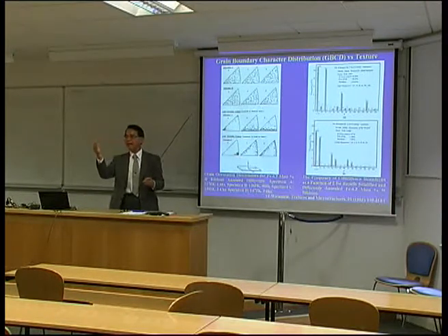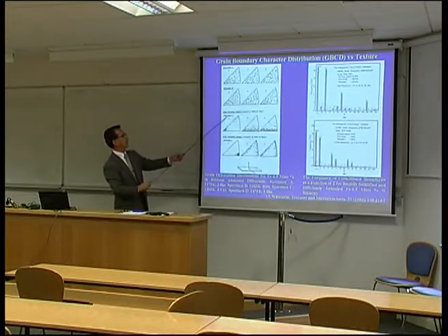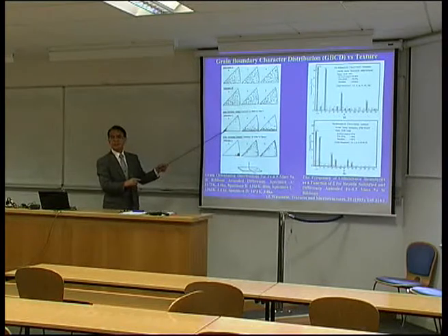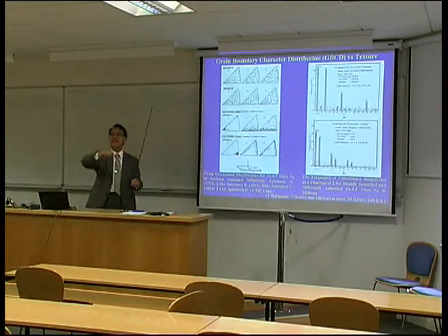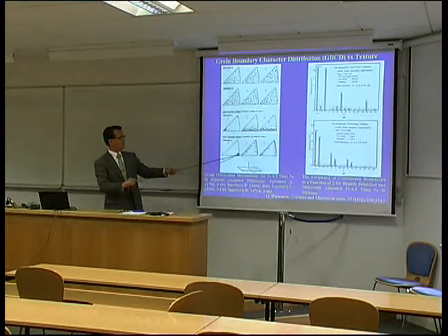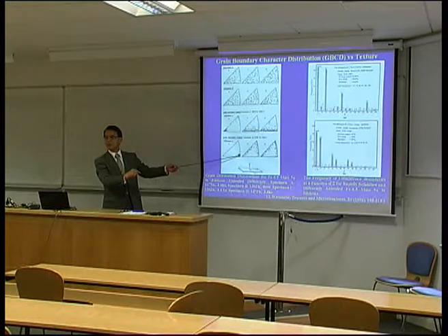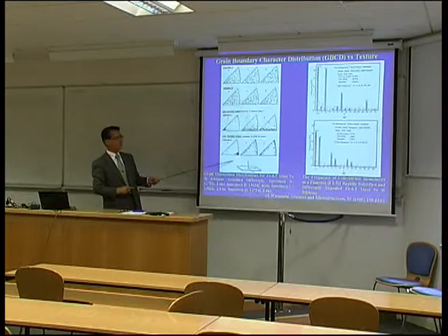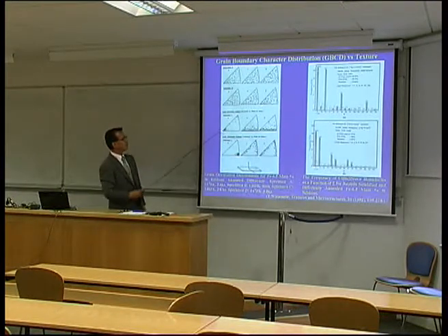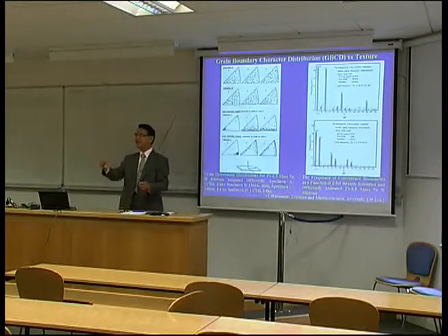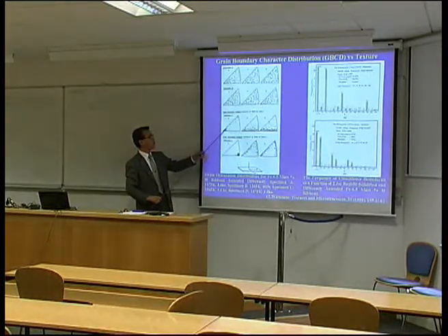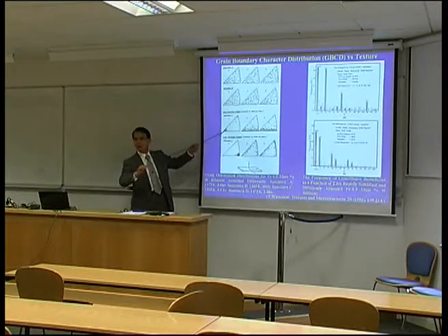But when we anneal this randomly oriented sample at about 1100 degrees C for 1 hour, we can get a very sharp 1-1-1 texture. But if we increase the annealing temperature just 100 degrees C up to 1200 degrees C, this time we can observe a very sharp 1-1-4 texture. So depending on the annealing temperature, we can introduce different types of texture. And if we characterize the grain boundary in the sample with a very sharp texture, within 5 or 6 degrees deviation from 1-1-4 only,